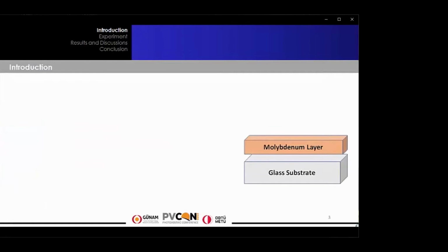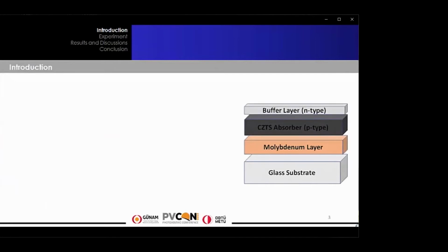In a photovoltaic device, the solar cell is composed of 4 main layers in addition to the substrate, which is generally made of glass. There is the back contact, which is an ohmic contact, in most cases molybdenum. The second layer is the absorber layer with P-type conduction. The third is the buffer layer. And the last layer is the transparent conductive oxide layer, in ITO or aluminum-doped ZnO.